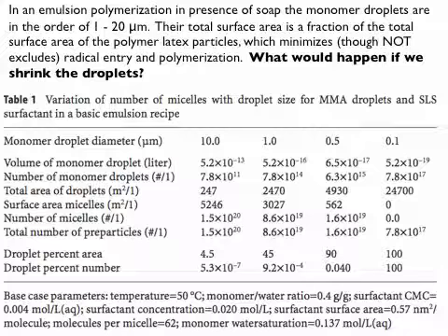And what if I make my monomer droplet diameter even smaller, to 0.5 micron, 500 nanometer? In that particular case, 90% of my surface area is a result of my monomer droplets, and I no longer have that many micelles left. And what if I can make it even smaller? What if I can make monomer droplets of 100 nanometer? If I have droplets of 100 nanometer, I have no more micelles left. Why not?